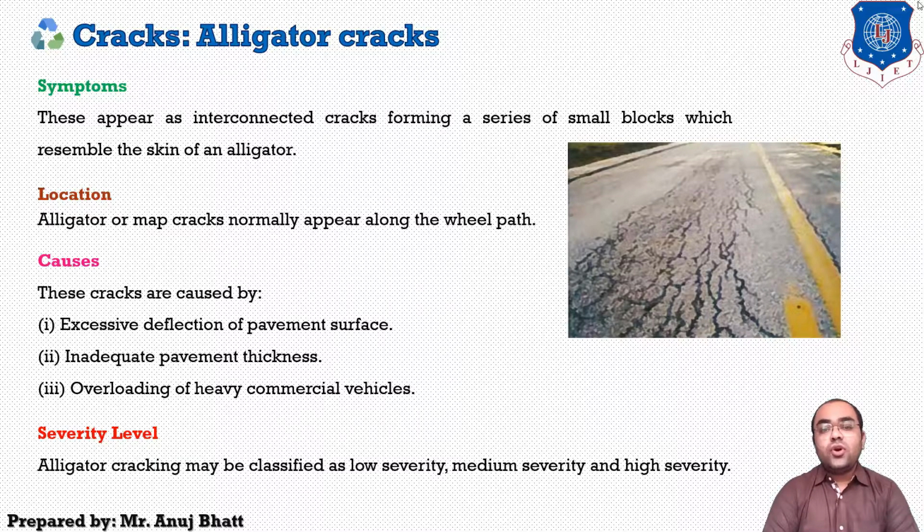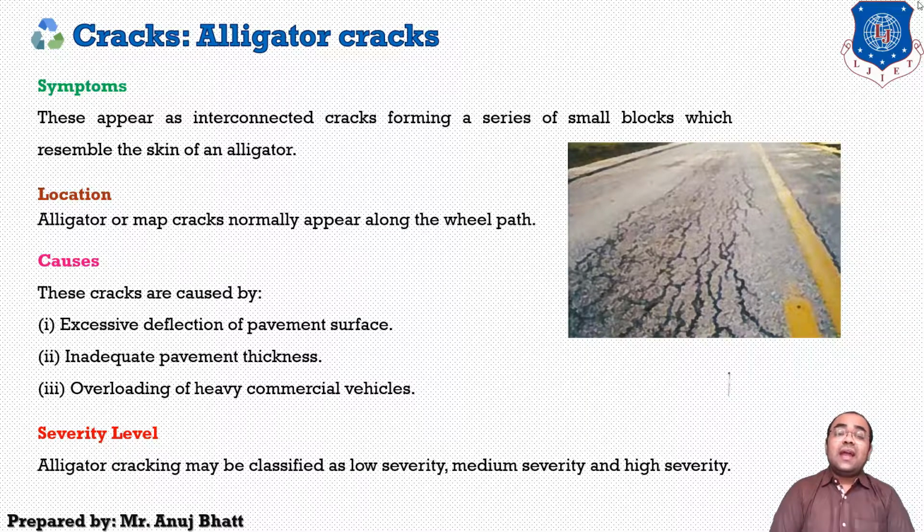There are many causes of alligator cracking. Let's discuss a few here. The first is excessive deflection of the pavement surface, normally in wheel paths. Next are inadequate pavement thickness and overloading by heavy commercial vehicles.